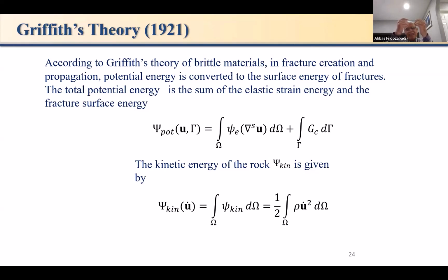After this breaks, suppose this is fully elastic, all the bonding is the same as before. So we have put a lot of energy into the rock. We have done a lot of work. Where did all this energy go? Here, Griffith's idea is that all this work we have done, all the energy has gone to a surface which has energy. So really, that's the essence of the argument.